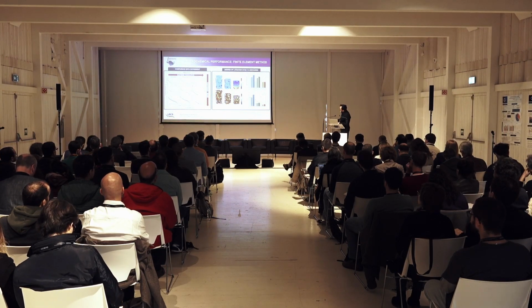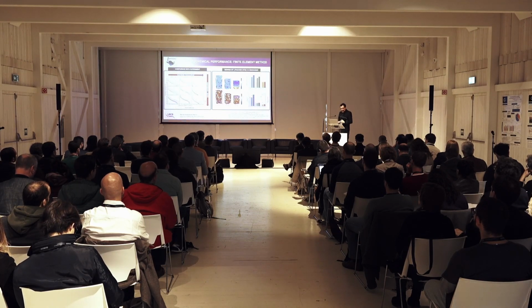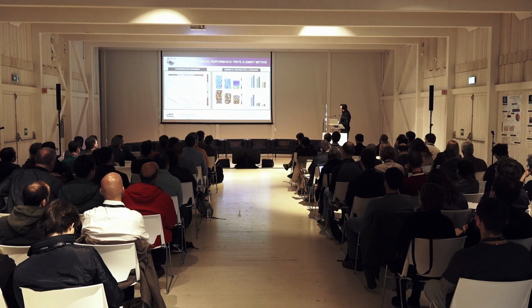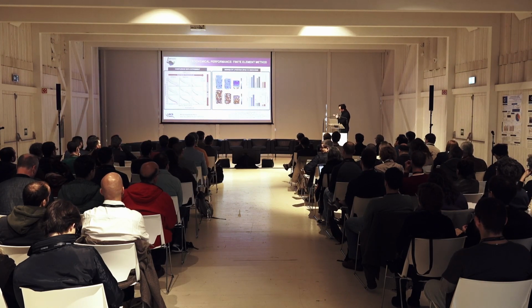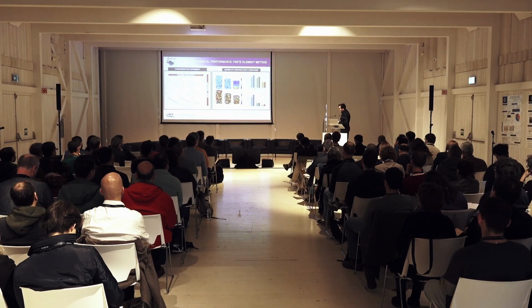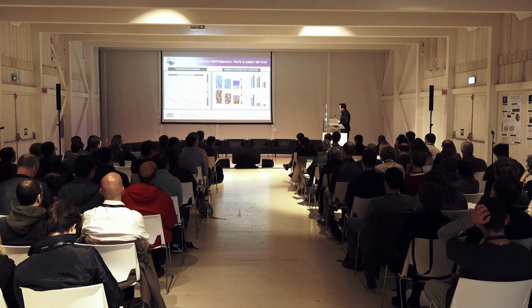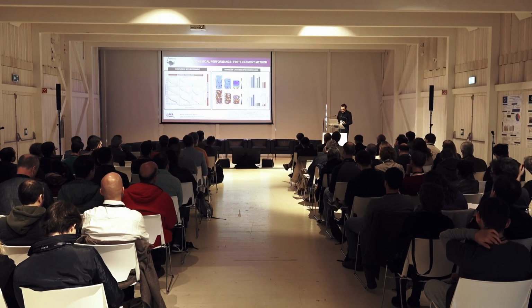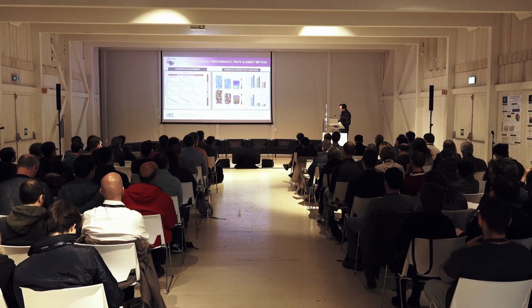Here we didn't change any parameter in the electrochemical model. The only thing we changed from case to case was the electrode microstructure. Okay? That means that through the electrochemical observables, we can also validate our manufacturing simulator. Right? Because you find a good match between the performance descriptors of the electrode microstructures and the experimental ones, so you can say, okay, I trust my manufacturing simulator enough, because we predict microstructures that then make sense electrochemically speaking.